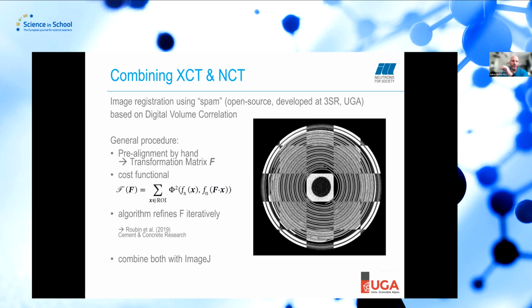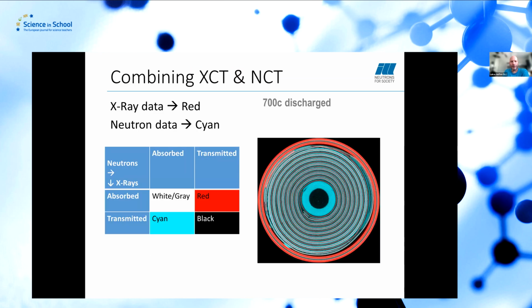For that, you can use an extension of digital volume correlation, that is a multi-modal registration. So you define a cost function, and then iteratively you align the images by getting to an extremum of this cost function, which depends on the joint or bimodal histogram of your sample. I don't go much into detail here, but what you get out is the aligned image. So you see very nicely highly X-ray absorbing structures in red. That's the copper current collector here, for instance, this small stripe. And the casing, of course, which is made of stainless steel.